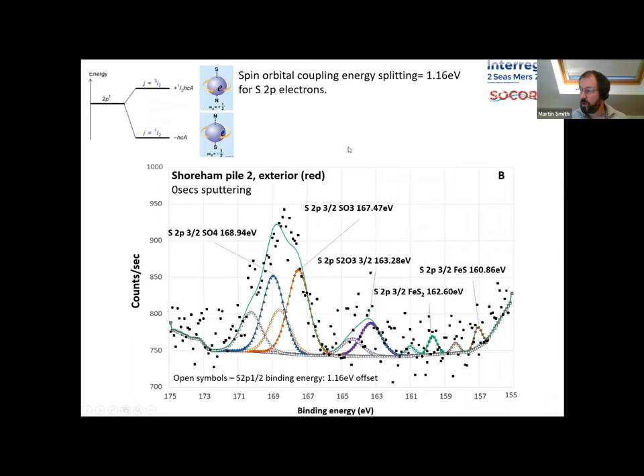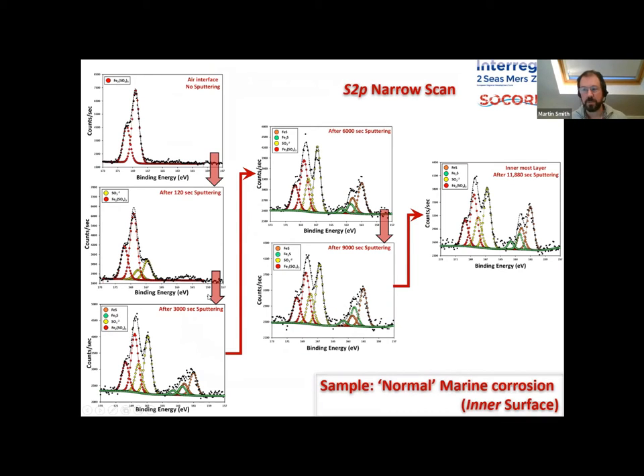If we look at a similar plot for the exterior of one of these blisters, the bright red parts, we lose the sulfide peaks. And now we can see very clearly we've got thiosulfate, we have sulfite, and we have sulfate. So we're capturing the whole redox chemistry of sulfur through a few millimeters of steel corrosion. And when we compile that over a whole series of sputtering experiments, we can see we go from an outer surface with iron sulfates, progressively higher concentrations of sulfides as we go in, and we get right into the inner surfaces that are dominated by sulfide minerals.